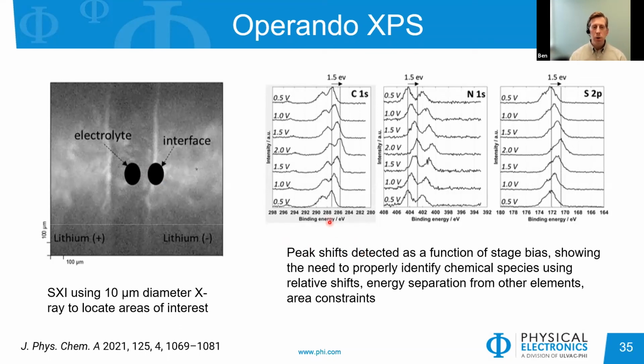And so what you do see is that peaks do tend to shift as we bias the sample from 0.5 volt up to 2 volts, then back. So this is where it would be important to decouple what you're seeing, charging effects on the overall spectrum versus the chemical changes. And so some of the things we talked about, like looking at relative peak separations and ratios between different peak areas that might be different states, would all be very important for your characterization.